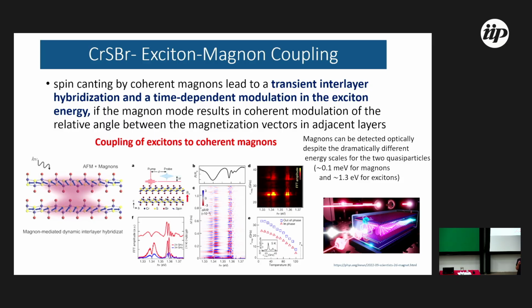Because of this property, it's a special material. It's not the case that all materials allow this. So you can measure the frequency, and it's exactly the frequency of magnons in this system. So it's a very nice system where excitons are coupled with coherent magnons. Okay.